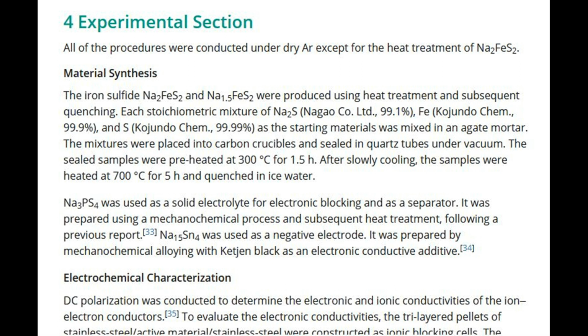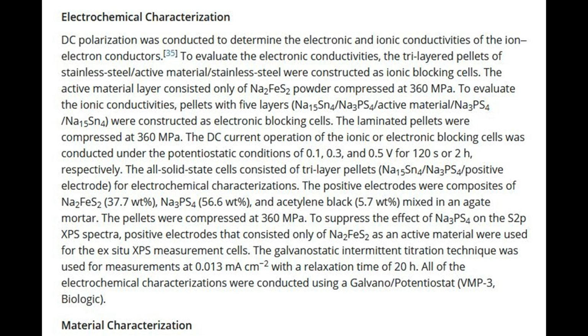To evaluate the electronic conductivities, the tri-layered pellets of stainless steel/active material/stainless steel were constructed as ionic blocking cells. The active material layer consisted only of Na2FeS2 powder compressed at 360 MPa. To evaluate the ionic conductivities, pellets with 5 layers, Na15Sn4/Na3PS4/active material/Na3PS4/Na15Sn4, were constructed as electronic blocking cells. The laminated pellets were compressed at 360 MPa. The DC current operation of the ionic or electronic blocking cells was conducted under the potentiostatic conditions of 0.1, 0.3, and 0.5 V for 120 s or 2 h, respectively.